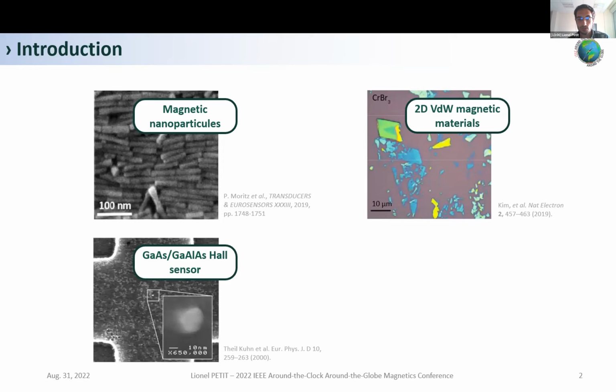A few years ago, people managed to make this kind of measurement with Hall sensors from epitaxially grown heterojunction structures. But it was at low temperature. Today, with the rise of graphene, we expect to be able to make the same kind of measurement, but up to room temperature.